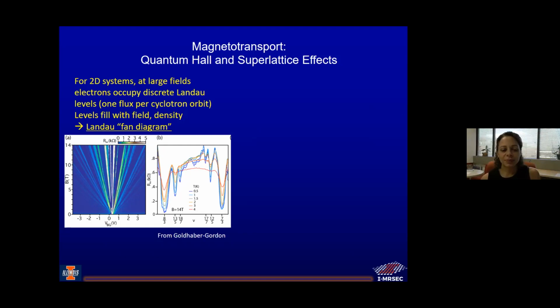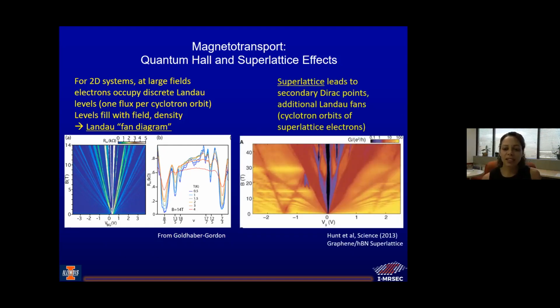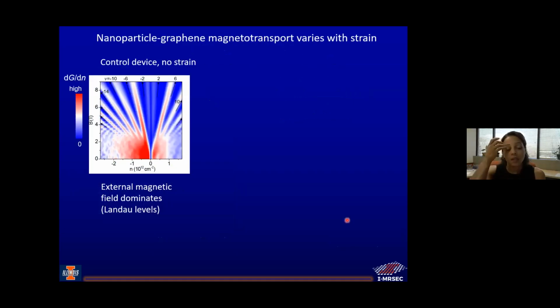Okay, so this has been seen in graphene, but when you have a superlattice, what you expect to see is this kind of Landau fan diagram around the Dirac point, but then secondary Landau fans around these secondary Dirac points, these superlattice points. Okay, so what do we see? Indeed, when we have no strain on our control device, we see these Landau fans. This is a high resistance point. This is a low resistance point, and here these numbers refer to the filling of the Landau levels. So this blue region is a plateau of 2, this is a plateau of 6. And this is exactly what you expect for clean graphene under a magnetic field with no strain.